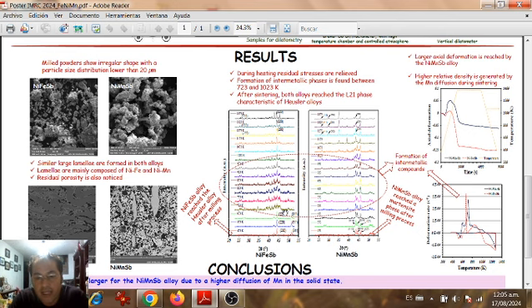We notice that the Heusler phase decomposes into different intermetallic compounds that are not at this moment identified. After that, around 1000 Kelvin, we notice that the ordering of the Heusler alloy is obtained. This is confirmed by the different peaks observed in the deformation rate during sintering. We can notice that these peaks correspond with the formation of the intermetallic compounds.